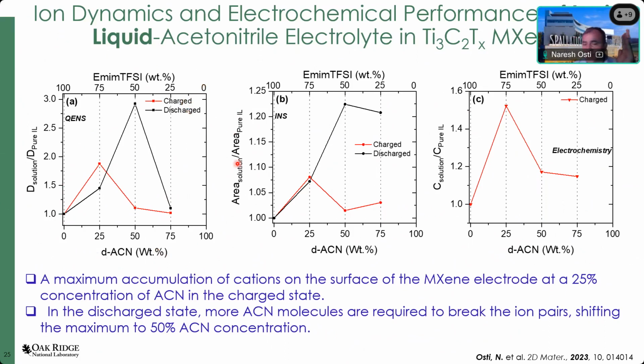That concentration is around 25% in the charge state. Now, once you have the discharged state, you don't have any external perturbation to the system. At that time, you need more solvent molecules to dissociate the ion pairs. That's why the maximum shifts to 50%. That's what we got from this particular system.